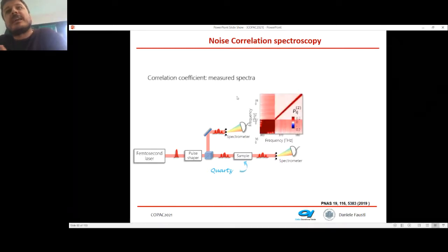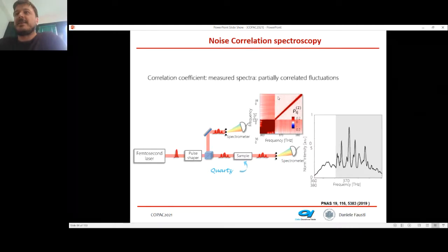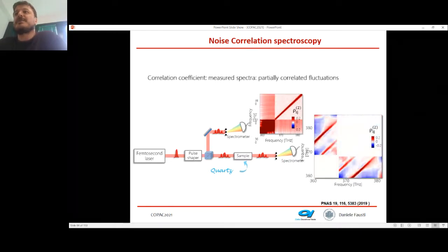If I do the correlator, I have a correlator where all the frequencies here are highly correlated and all the frequencies here are uncorrelated. And if I measure the Raman response, I see basically that I can measure even very weakly scattering phonons. It's a relatively sensitive technique where you can actually address the frequency of your modes on ultrashort time scales.